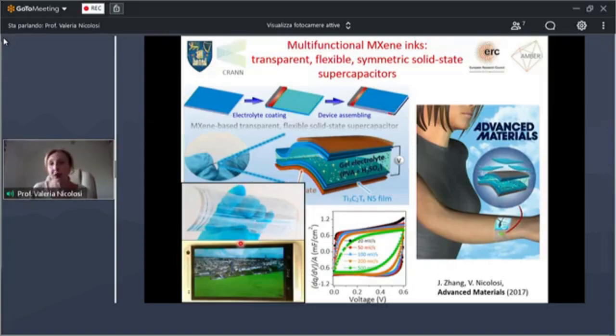And whoever works with supercapacitors knows that it's very easy to build very small micro supercapacitors, but once you actually have large area supercaps, they don't work very well. In this case, because of the electrochemical performance of MXenes, their electrical conductivity, and their mechanical stability, we managed to assemble very, very large area devices, fully transparent, 98% transparency. Here, this device is superimposed on my postdoc's mobile phone to show full transparency.